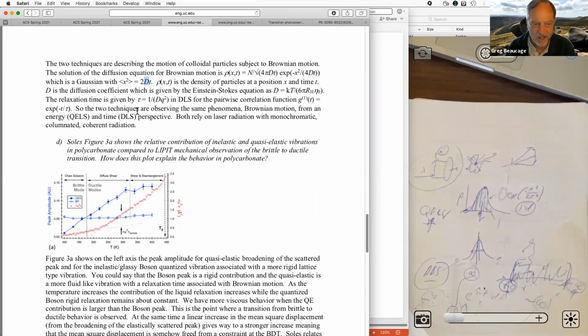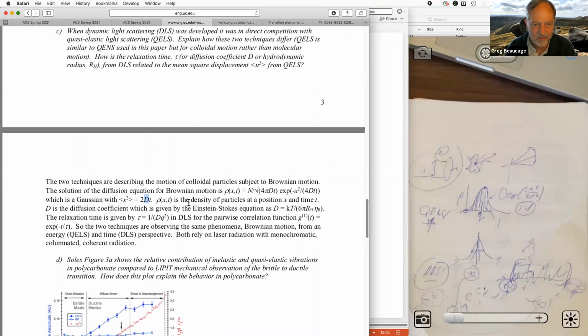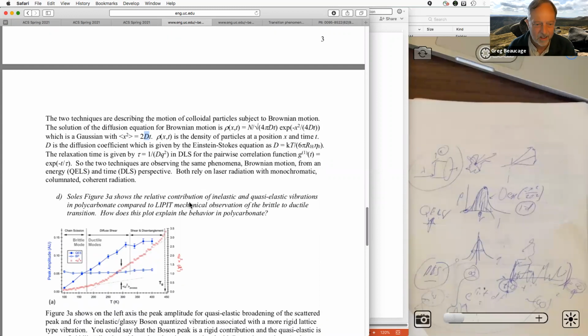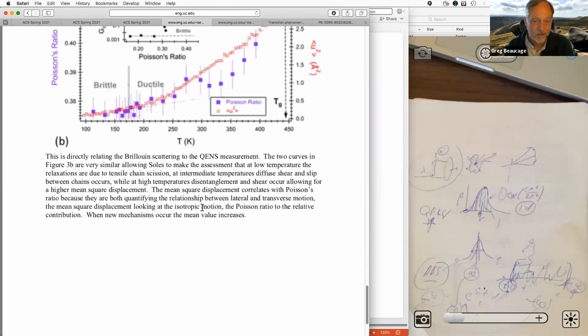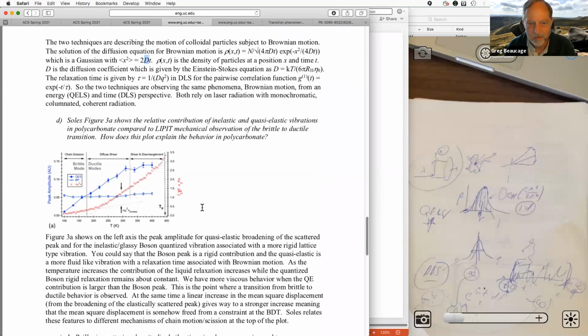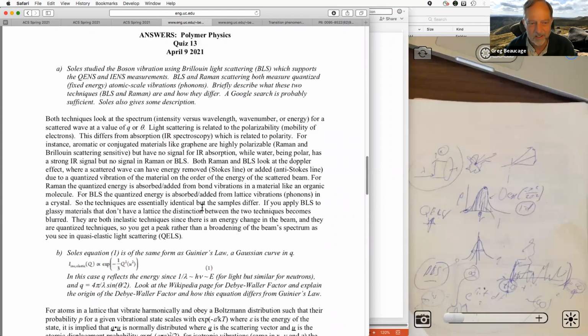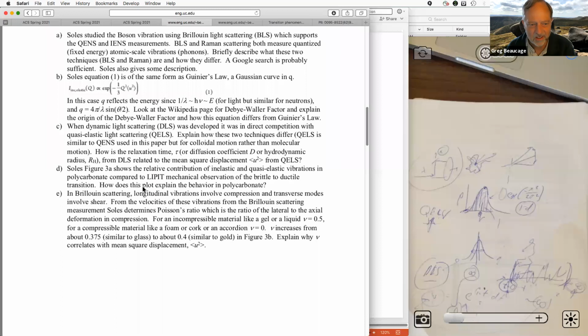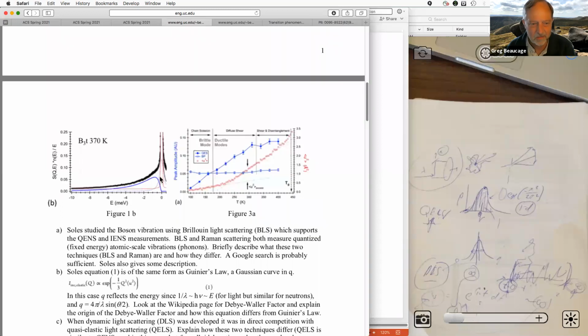But the broadening is fine. So you can see that they can measure the broadening. Right. So anyway, that's why they probably would prefer not to do this kind of measurement, because look how sketchy it is. You know, it's too mushy. You're just doing these multi-parameter fits to this broad blob, right? Whereas in DLS, you see a nice exponential decay. So if you have complicated systems here, they tend to smear into it.